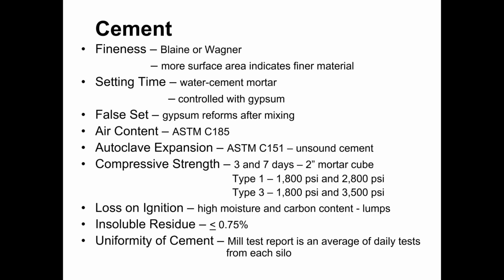And there were some instances where the blocks would come out after initial curing and look fine, have sufficient strength, but then over a period of days, weeks, months, the concrete would kind of self-destruct. It would start falling apart. They referred to this phenomenon as unsound cement, and they developed this test, ASTM C151, as an indicator of whether or not the cement would perform this way. But anymore, we don't see a lot of hot cement being shipped out to buyers. That's one of the reasons why we don't see this occurring very much, and also just the tighter controls on the raw materials and the manufacturing process that goes into cement production.